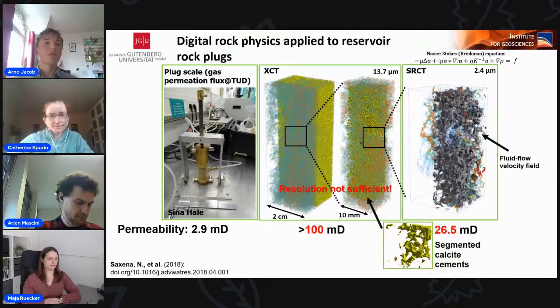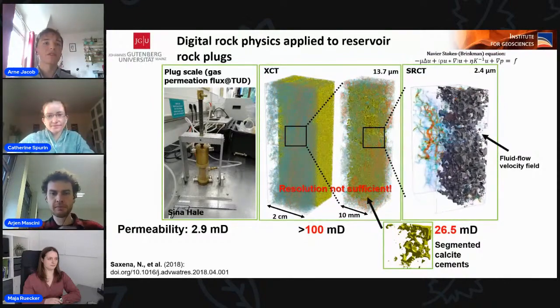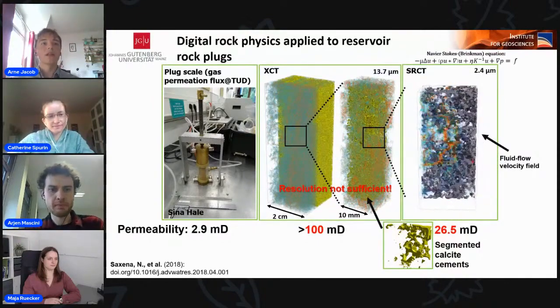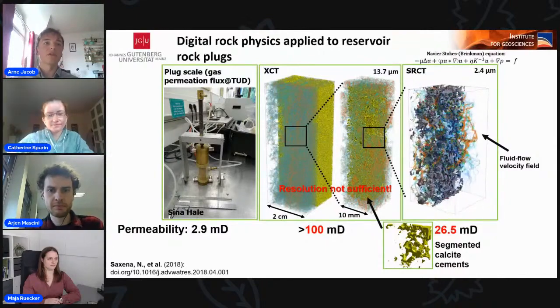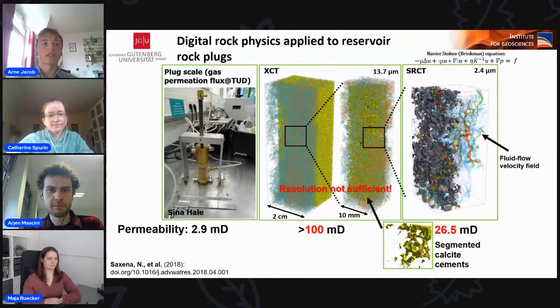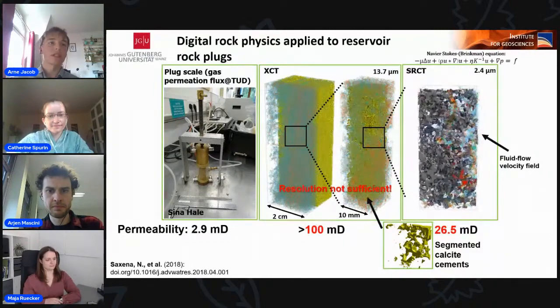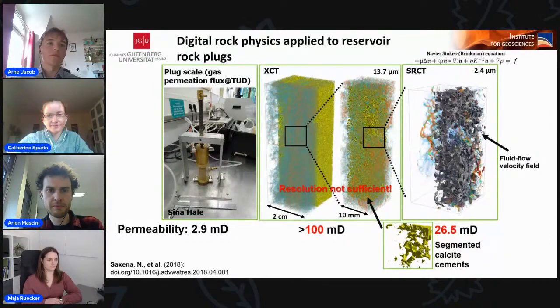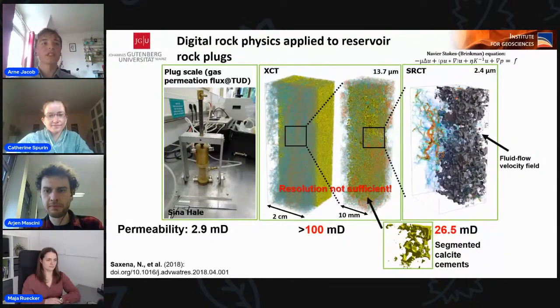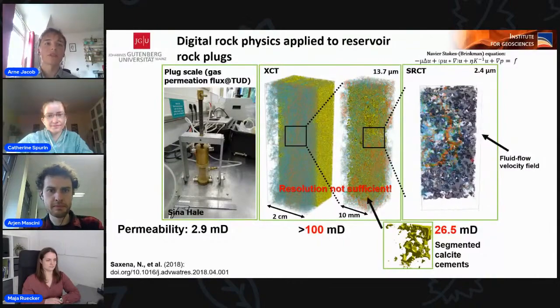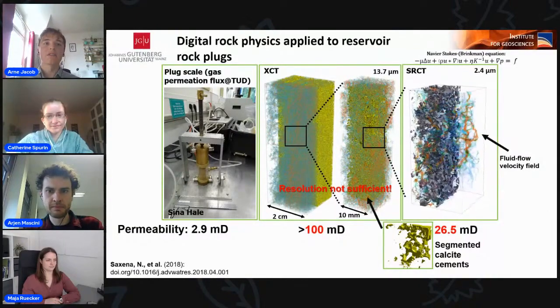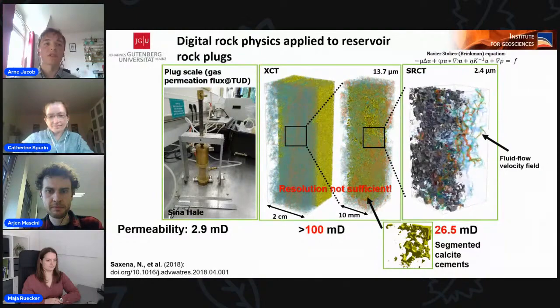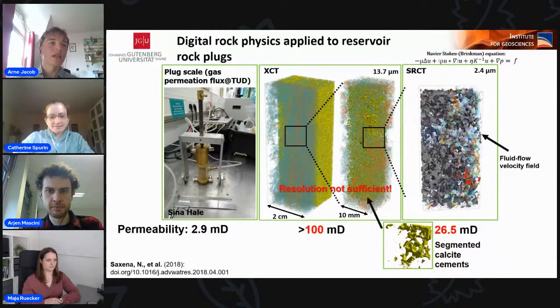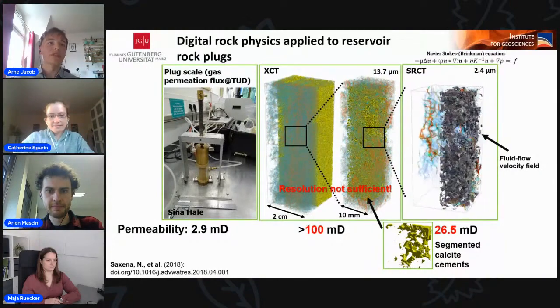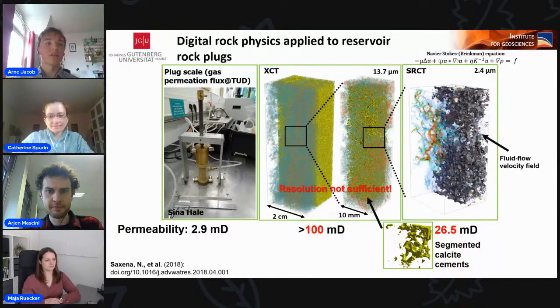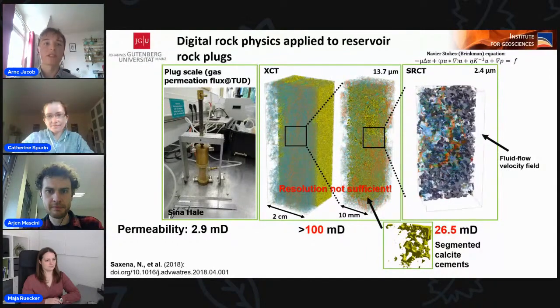We obtained a mean permeability of 2.9 millidarcy for the big plug samples. And in the middle, you can see a rendering of these big plug samples with visualized calcite content in yellow. And the fluid flow velocity fields, which was obtained by applying the Navier-Stokes equations using the highly advanced solvers of GeoDict. These samples in the middle were scanned by using conventional micro-CT imaging with a resolution of 13 micrometers.